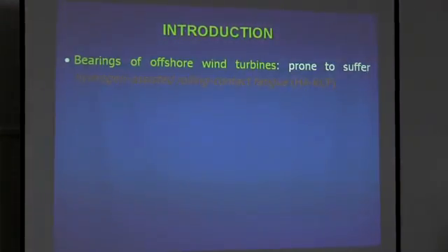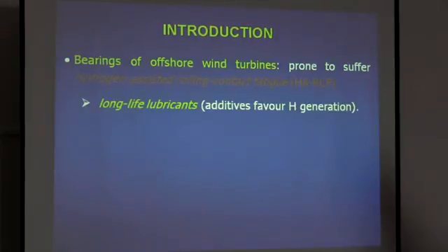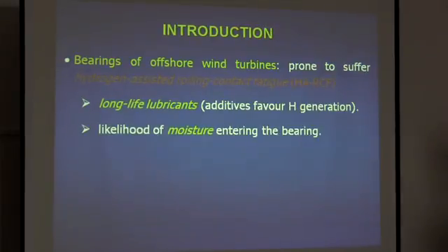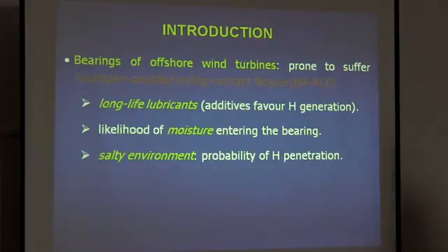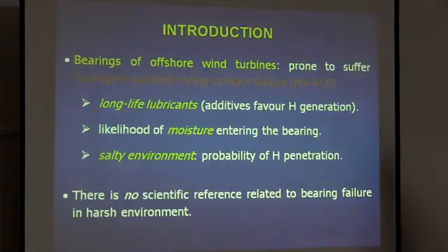Summary, introduction. The problem is that bearings of offshore wind turbines are prone to suffer hydrogen-assisted rolling contact fatigue, HARCF, because of long-life lubricants, additives favoring hydrogen generation, and the likelihood of moisture entering the bearing. A very confusing and complicated problem. Salty environment with probability of hydrogen penetration, and there is no scientific reference related to bearing failure in harsh environment.